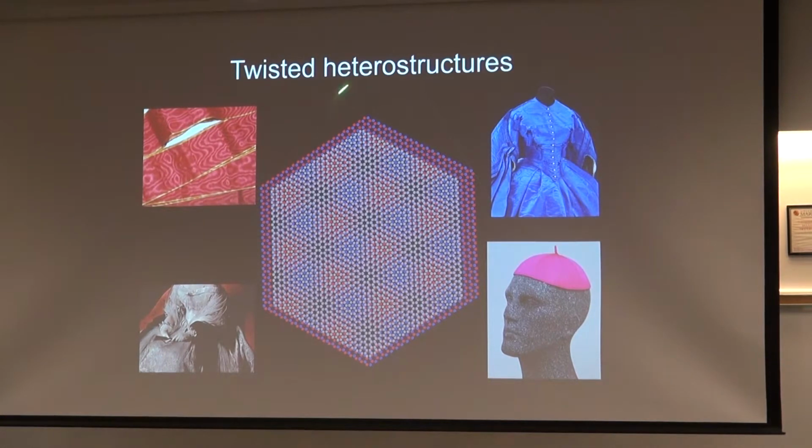In particular, if you take graphene and align it rotationally to boron nitride, that intrinsic lattice mismatch of a couple of percent gives you some long wavelength period. I don't know if it resolves from your angle, but you can see there's some pattern much larger than the lattice constant. This is exaggerated. In fact, it's more on the order of 50 lattice constants. This is a Moiré pattern, the same pattern that goes into Moiré silk, which mostly went out of fashion 100 years ago, but is still de rigueur in clerical headgear, I discovered from a Google search. Anyway, this is a simple beating of these two mismatched lattices.